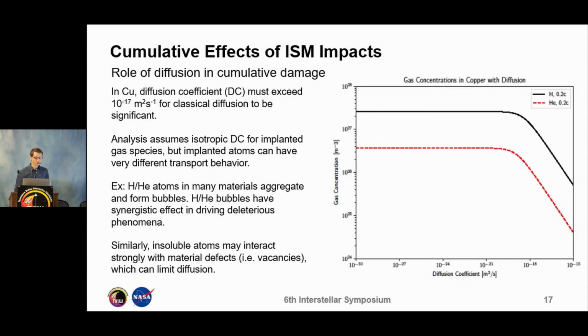In copper, the diffusion coefficient must exceed 10 to the negative 17 meters squared per second for classical diffusion to be significant. And diffusion is significant when the diffusion length becomes comparable to the straggle of the implantation distribution. This analysis, of course, assumes an isotropic diffusion coefficient for various gas species, but implanted atoms can behave differently because they have different transport behavior when other species are present, or if there are lattice defects in the target.